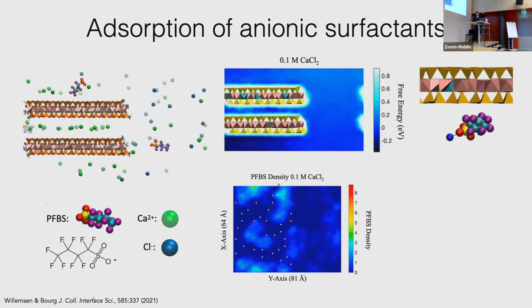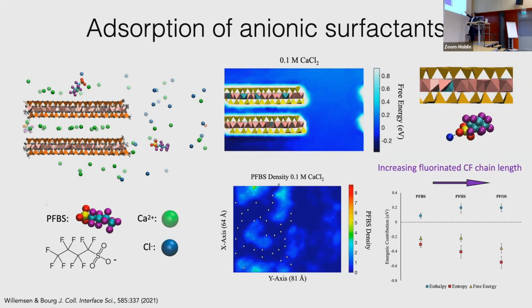So the calcium is not bridging the organic compound and the mineral surface, although it is kind of stabilizing the adsorption. And again, the main contribution to the adsorption is this entropic contribution, water wanting to spit out the compound. The specific interaction with the surface, this enthalpic contribution, is actually unfavorable, although it's less unfavorable in the presence of a divalent cation. It's unfavorable as we would expect because the negatively charged compound is interacting with the negatively charged surface.